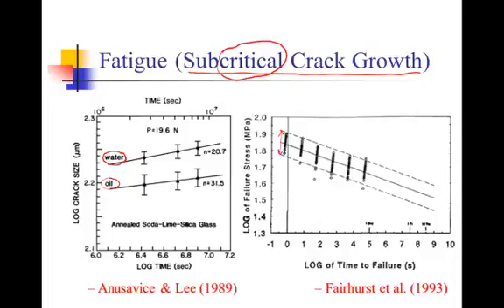However, he didn't use a constant rate of stressing. He had some groups of specimens he tested very rapidly, and some he took a long time to test, up to 1 day. And what he found was that when he took up to a whole day to test the specimens, the average strength of the specimen was lower than when he tested them quite rapidly. And the strength got lower and lower the longer period of time that the specimen was under this increasing level of stress. And so the cracks were growing over time during the test. That's what caused the change in the average strength.